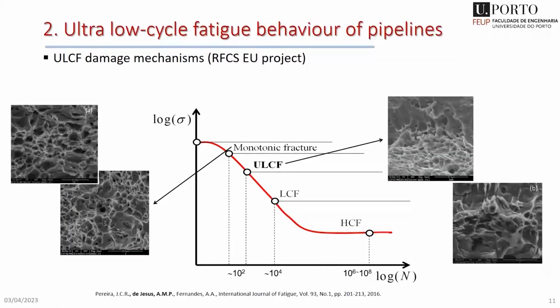So about ultra-low cycle fatigue, we are talking of a damage mechanism in the transition between what we know as low cycle fatigue and the monotonic fracture. And on the left, you can see a typical fracture surface from a ductile steel, where you can see this dimple type of microstructure. And on the right, you can see what we could get from an ultra-low cycle fatigue testing, where in this cyclic testing, we can also find some dimple formations, which tell us that we are talking of a transition damaging mechanism.